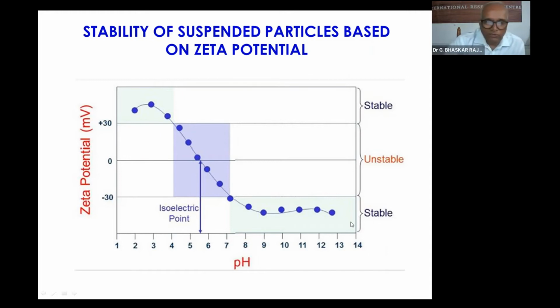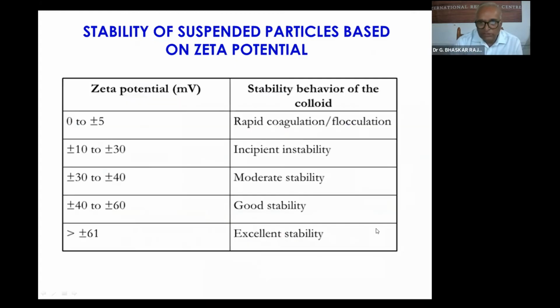That means when the particles have a zeta potential of about 30 millivolts, you can expect a stable dispersion; you can suspend them in the liquid. So then, next, what is the zeta potential? Here it is 0 to plus or minus 5 millivolts. It is rapid coagulation or flocculation. That means the dispersion won't be there.